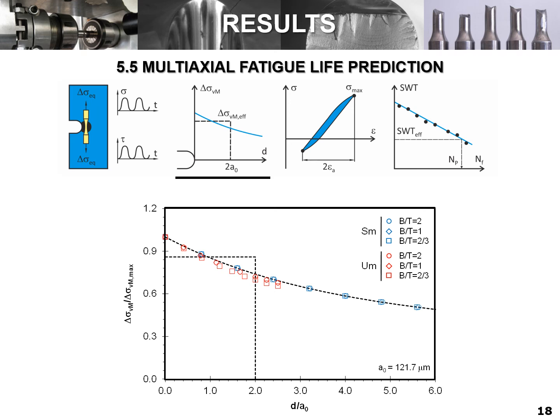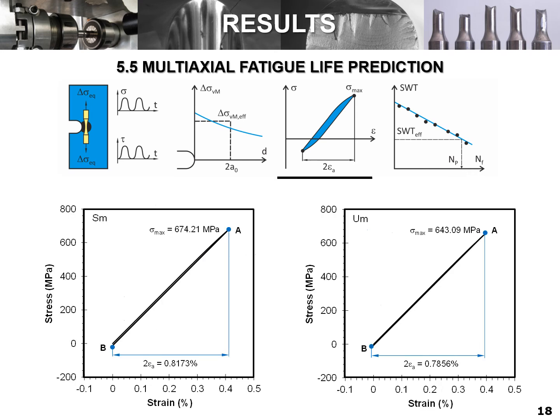The next step is the computation of an effective value of von Mises stress range at the initiation site. In this work, this was done by applying the line method of the theory of critical distances. The figure compares in a dimensionless form the evolution of the von Mises stress range with the distance from the hole surface along the critical direction for the different BT ratios.